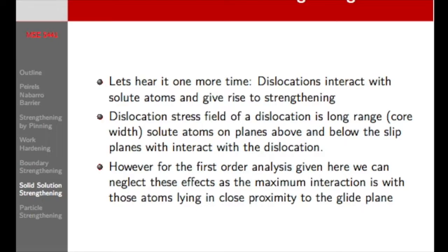And the latest research and simulations are showing that it basically behaves just like a regular substitutional solid solution. There's nothing going on there that's actually different than the basic theory that we're going to talk about for dilute solutions. It holds until it phase separates. If you phase separate, then of course the solid solution strengthening falls apart.